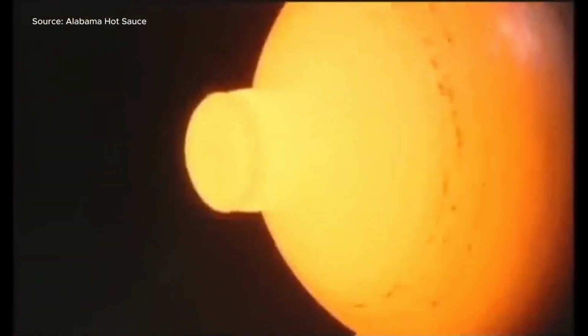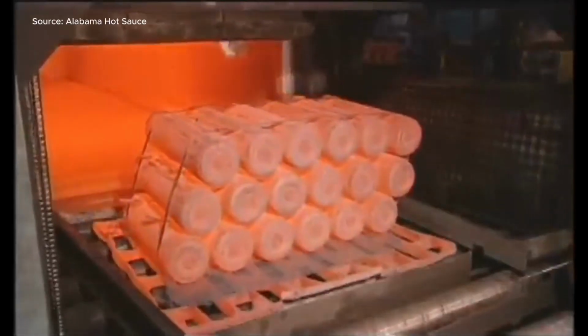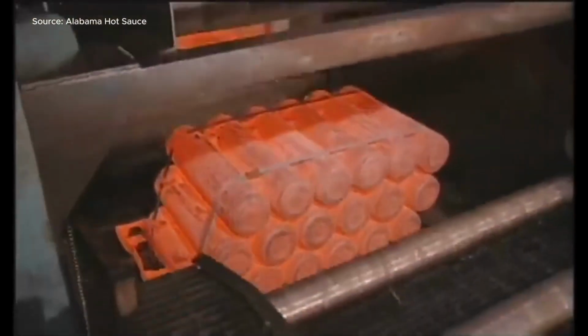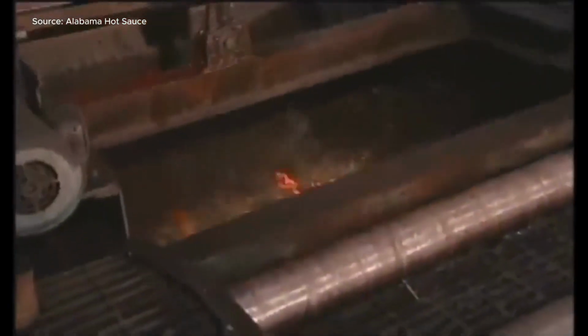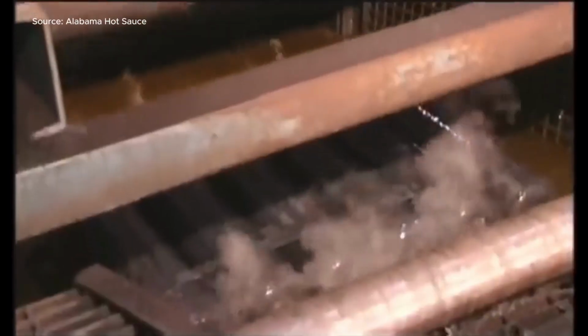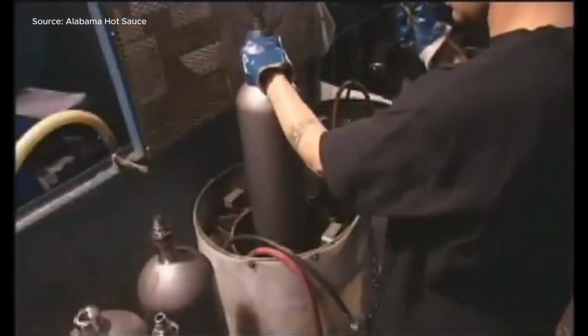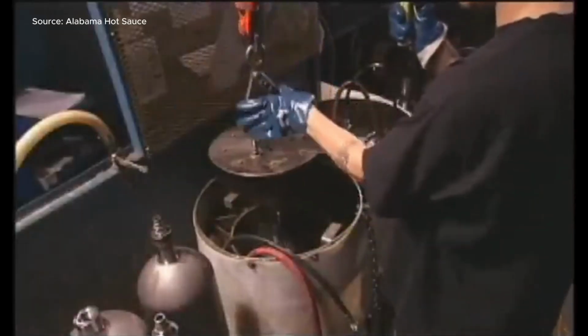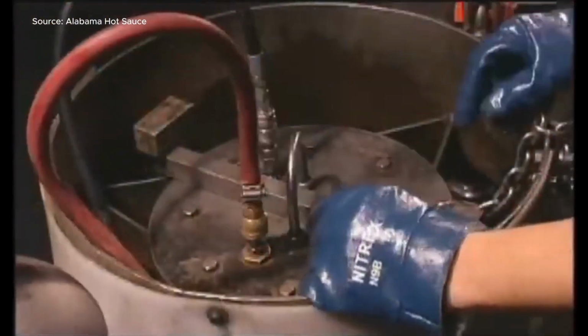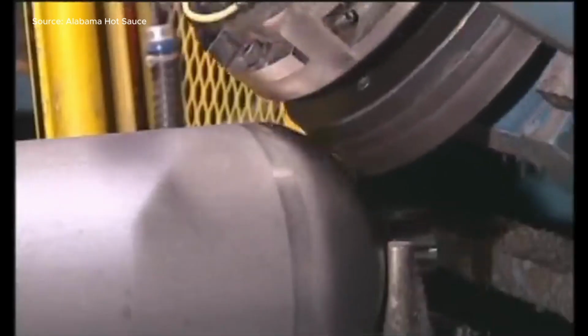Following heat treatment in a computer-controlled furnace, the cylinders are machined to add internal threads and O-ring grooves. They undergo hydrostatic testing, with cylinders pressurized to 5/3 of the service pressure. After testing, the cylinders are cleaned, shot blasted, and coated with a corrosion-resistant primer, followed by hot dip galvanizing for added protection. Finally, they are marked with regulatory information and packaged for shipment.